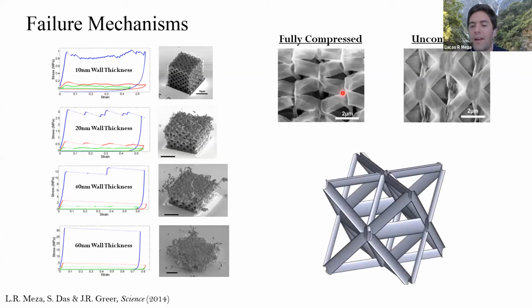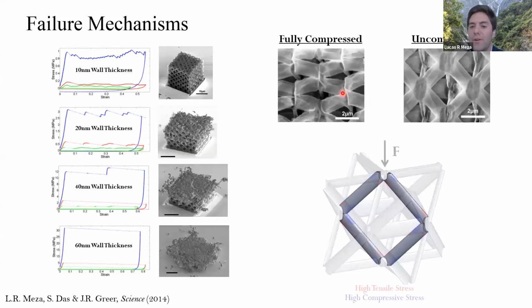So here we can determine a transition between those two behaviors. If you look at a cross section in compression, you have regions of high tension and high compression. Basically you have a competition between rupture in the areas of tension and buckling in the areas of compression.